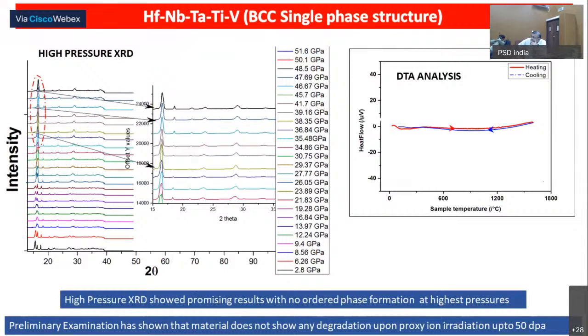When we did the DTA analysis, we went up to close to 1400 degrees centigrade, back and forth several times, with no phase transformation, no change, no formation of a peak or any enthalpy change. The BCC structure is rock solid up to 1400 degrees centigrade. Then another issue was to test the same material under high pressure. High pressure means I am going close to 50 GPa, and after crossing close to 45 GPa, a little bit of another phase forms, but the major structure remains BCC all along. These are in situ XRD taken under changing pressure, and you can see the material does not show any degradation up to 50 GPa. Sorry about that.